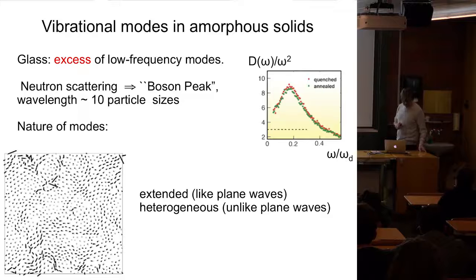I'm sure Andrea told you about this, but okay, that's for a crystal. If you look at glasses, you find something different. Compared to their crystalline counterparts, glasses tend to have more soft elastic modes. One way to look at this is to plot the density of vibrational modes divided by omega squared. That should be just a straight line for a crystal. What you find in glasses is that this has a hump, and this hump, it's a fancy word, is called the boson peak.